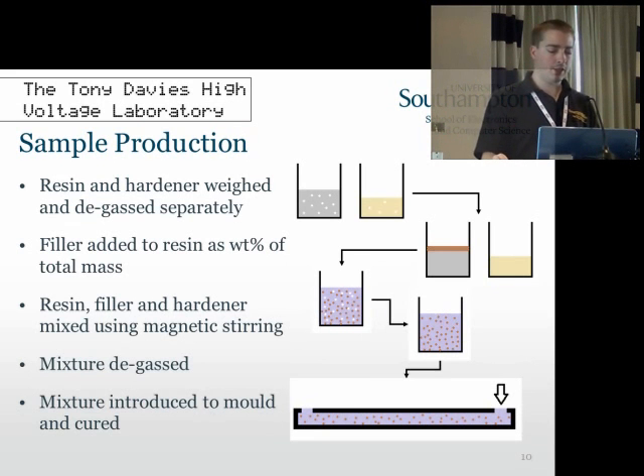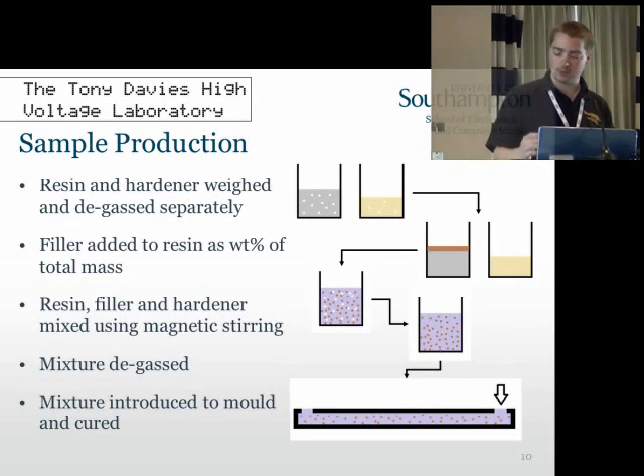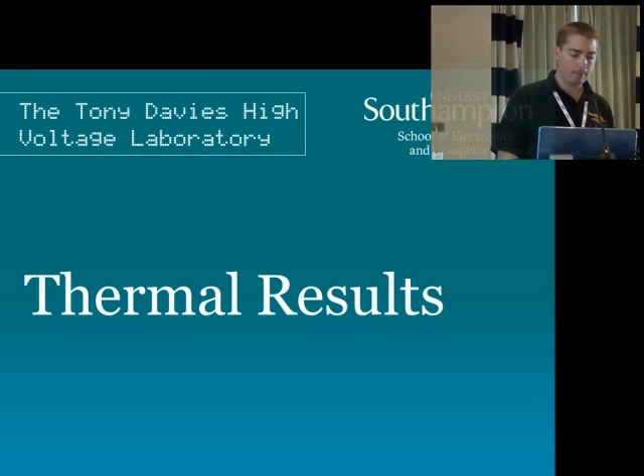The main aim for this is simply to see how easy it is to disperse these in a system. We're not aiming for perfect dispersion. We haven't used sonication or anything advanced like that at this stage. We just want to see in an industrial scene how easy it would be to produce these on a large scale. We then obviously degassed the mixture because the mixing will introduce air pockets. Introduced that to a mould and cured it to produce a thin film sample.